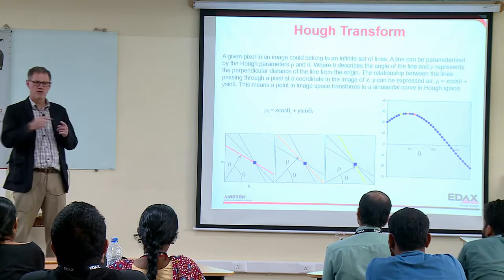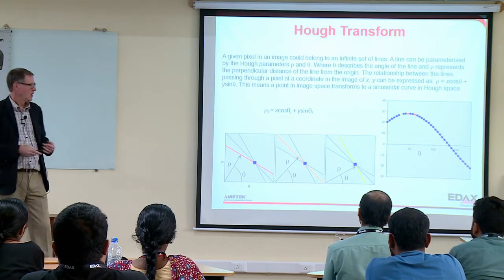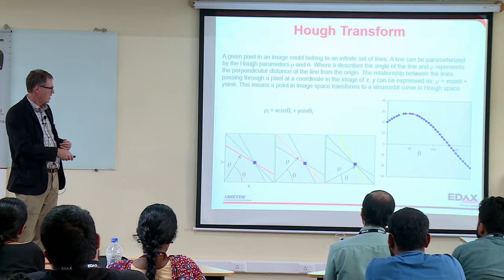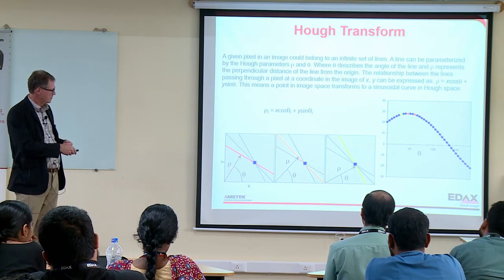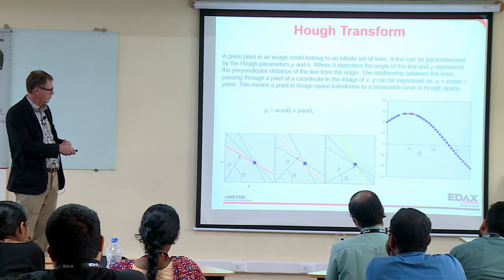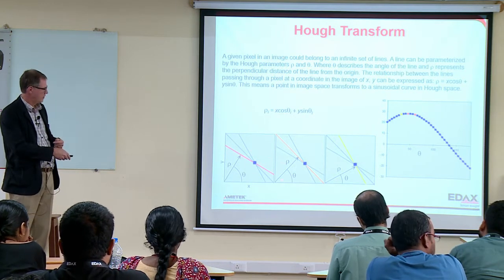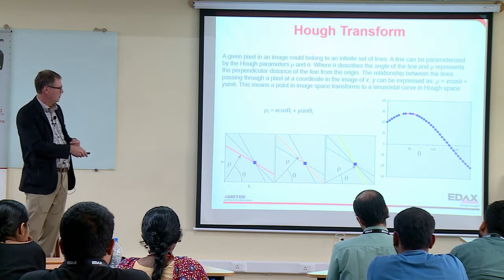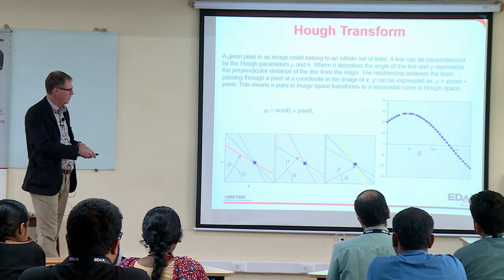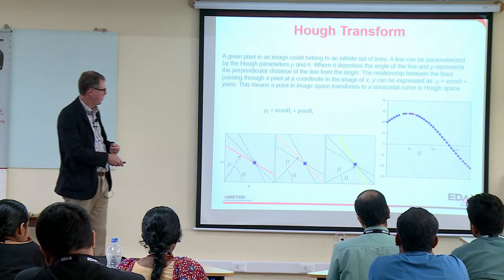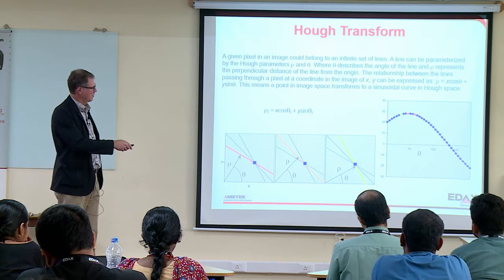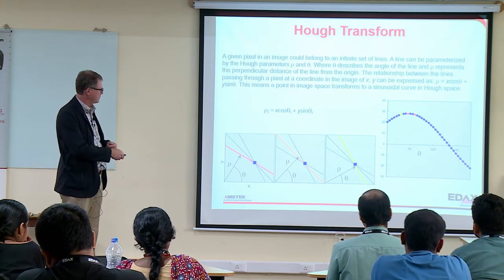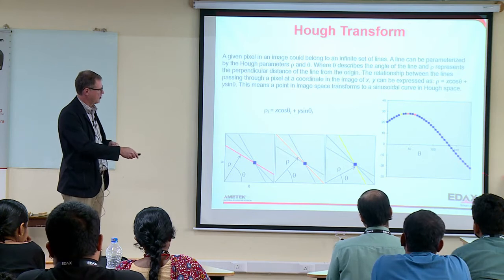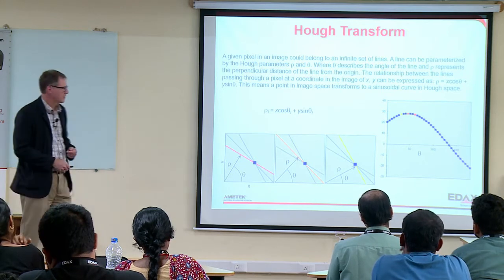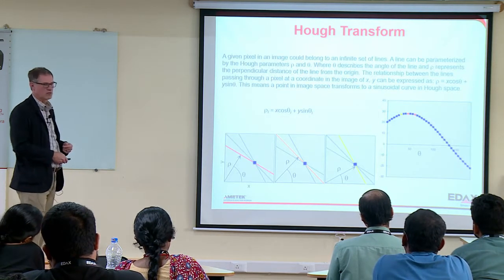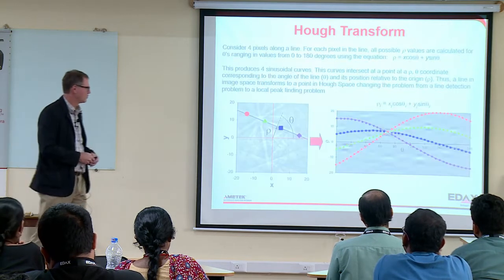The way this works is, for a pixel in my pattern, there's an infinite number of lines going through that pixel, right? You can define each one of those by an angle and the distance from the origin of a normal to that line. So for this red line, I get one rho theta pair. For this orange line, I get another rho theta pair. For the yellow line, I get another. If we do that, a pixel becomes a curve in Hough space. It seems like we're making it more complicated, but trust me, it will work.